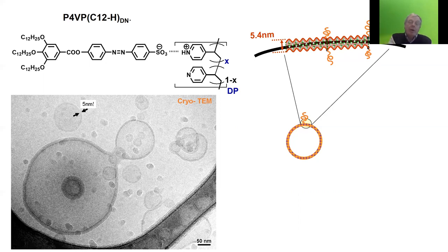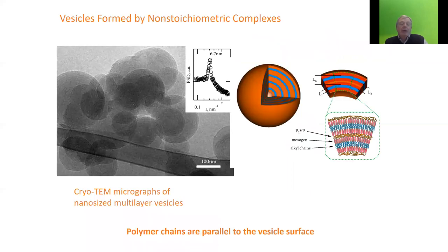So now we have a polymer where the vesicle formation is more stable because of the polymerization, because of these backbone chains which run along the vesicle membrane, but still they are compatible with the natural lipids. And you could introduce proteins and membrane proteins into the membrane and play with this. These things form multilayer vesicles, and you can play with those multilayer vesicles.